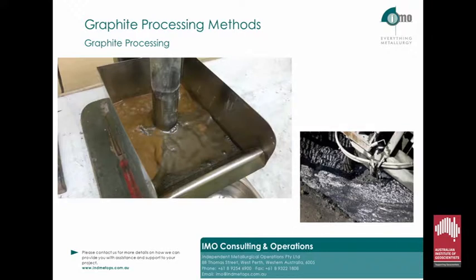Graphite itself is naturally hydrophobic, meaning it does not like water, but it still needs a little help in terms of recovery. Oxide flotation, which graphite is characterised into, is often difficult as the collectors used will attach to and recover some of the gangue minerals. But with graphite, it's fortunate that the collectors used will generally only attach to the graphite, enabling a high-grade concentrate at excellent recoveries to often be achieved, again providing the graphite is liberated.